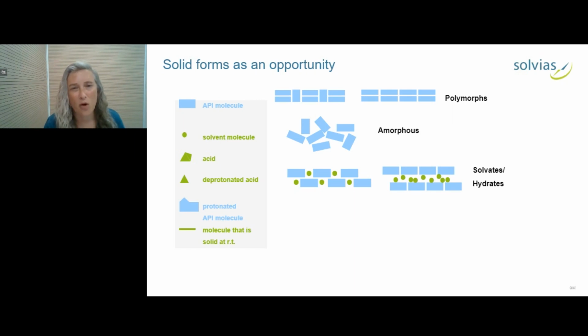So what you can have is a host-guest complex between your drug molecule and a solvent, and that can be either an organic solvent that is used in crystallization, and that's a solvate, or it can be water, in which case it's known as a hydrate. And you can have different solid forms, basically different polymorphs of solvates and hydrates. You can also have stoichiometric solvates and hydrates, where there is a defined ratio between the solvent molecules and the API. Or you can have, in particular in the case of hydrates, channel hydrates, so structures with channels where the molecules can diffuse in and out. And these can be complicated to develop, but you'll see an example later on. So you can have polymorphs of solvates and hydrates.